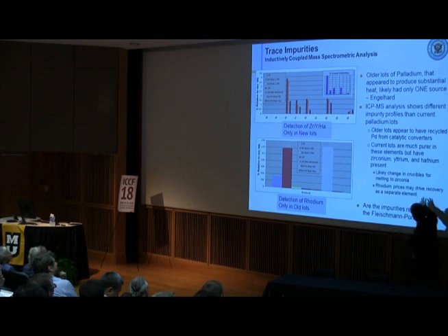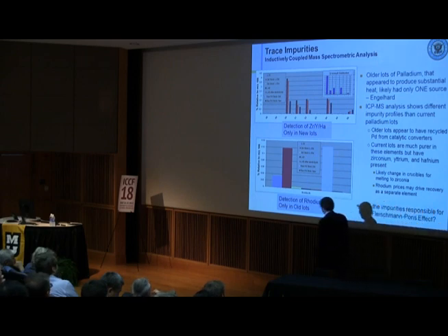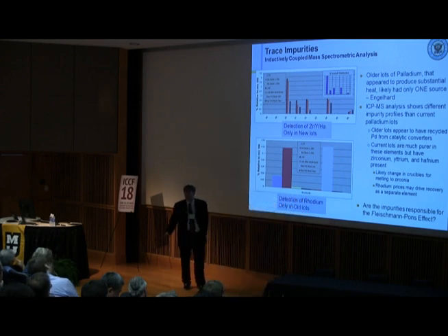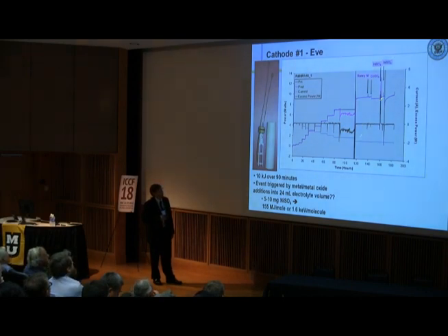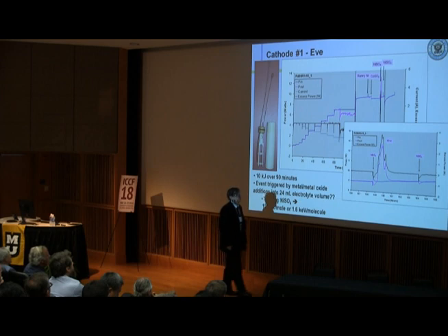They also changed how they melted it. Now they're using zirconia crucibles. In the old days, they used alumina crucibles. So the impurities are different. So we said, rhodium. Well, this is parts per million. We're going to put more in. We're going to put in 10%. If a little's good, a lot's better. And we picked 10% for a reason, because it's on a phase boundary. And so we ran our samples, and we made some additions, Raney nickel, cobalt nickel, and lo and behold, we saw this. The first one out of the box, we saw this.